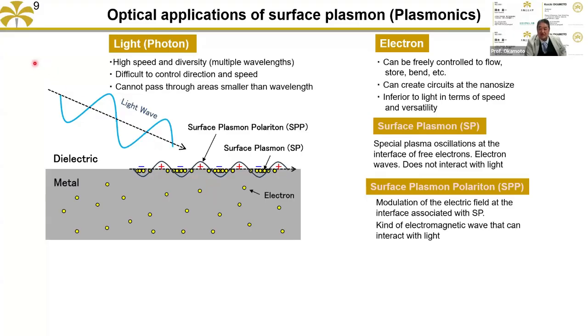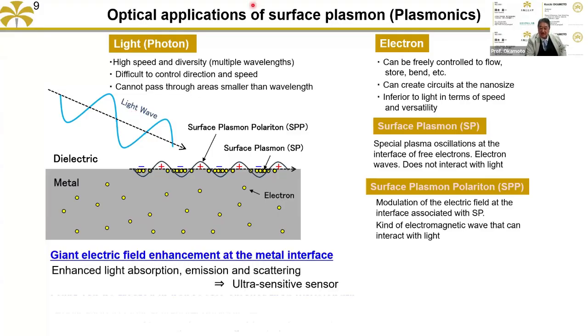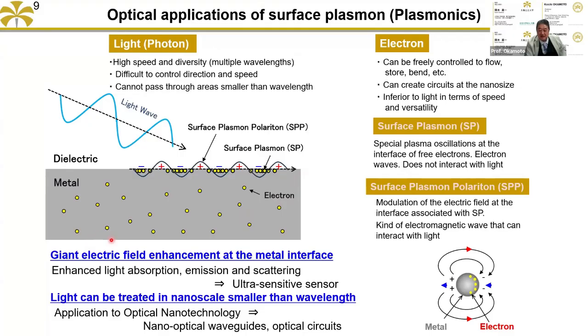So if you shine the light at the interface, usually it's deflected or diffracted, but here the light is confined at the interface. Then you can obtain a giant electric field enhancement at the metal interface. Sometimes it's a million times larger, something like that. And it enhances light absorption, emission, and scattering near the interface. Then it should be useful for ultra-sensitive sensors, like an SPR sensor or surface enhanced Raman spectroscopy.